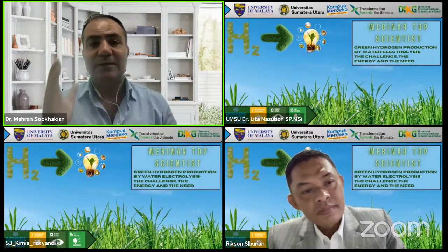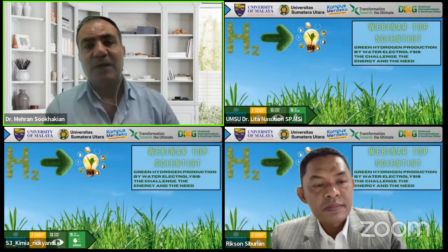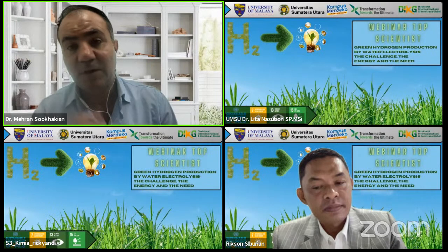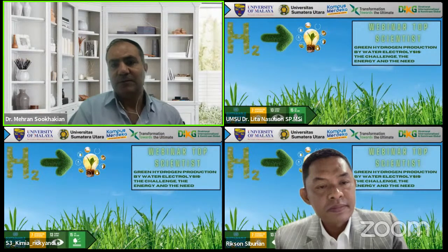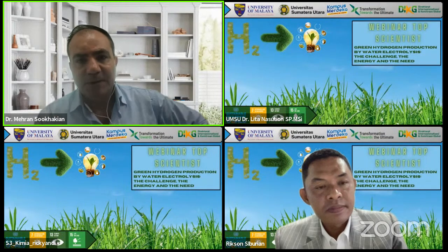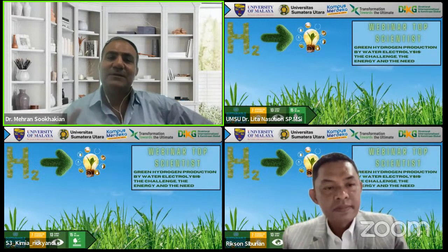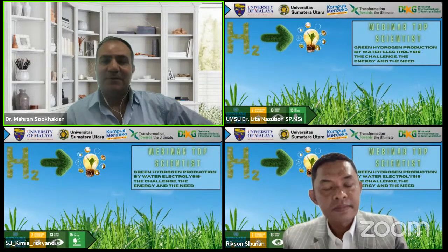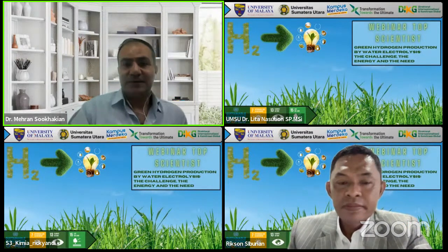But in Raman spectra and XRD, we have impurity of molybdenum oxide, especially in Raman spectra. We try to produce monolayer molybdenum disulfide with high purity. This is the challenge in our CVD. Around 4 years ago, I visited NTU, National Taiwan University, under a collaboration with Prof. Chen. He is very expert in CVD, the growth of different materials. Their CVD works with three different temperature zones, and they produce very high quality and high purity different types of 2D material, like tin sulfide. This is the challenge in our research right now.